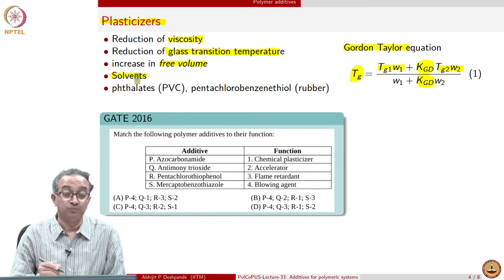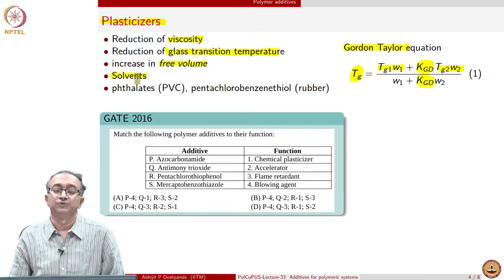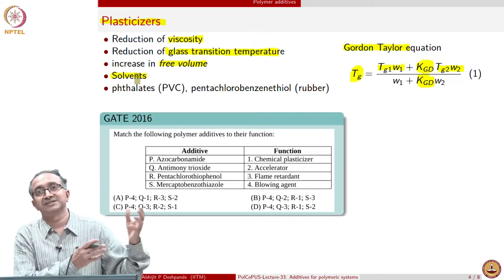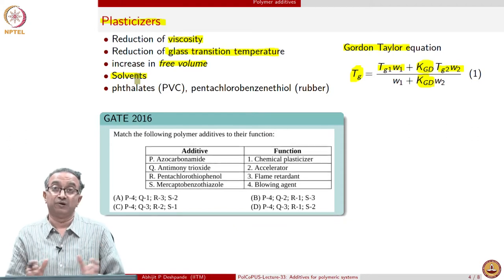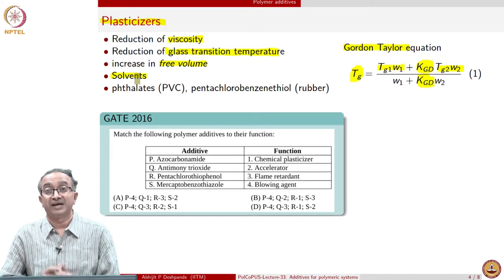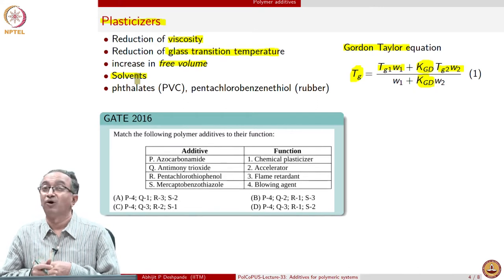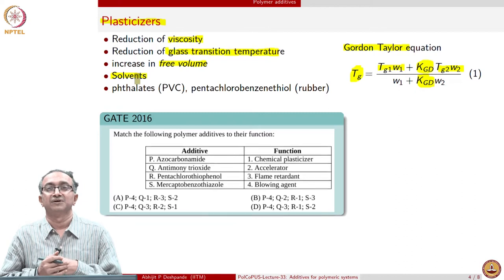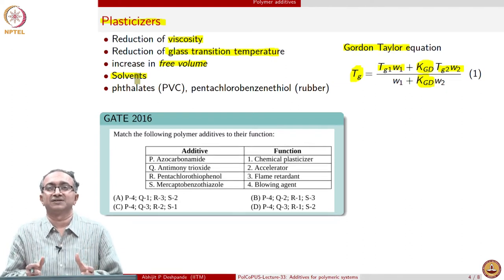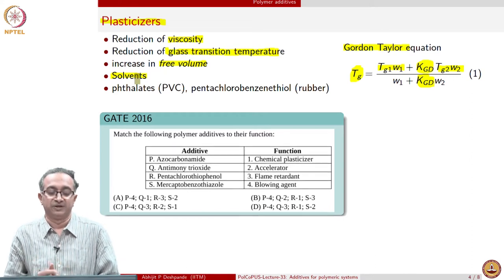Solvents and also monomers themselves can also play the role of plasticizers. Small molecules intentionally added as plasticizer, but also residual monomers and residual solvents remaining as a consequence of polymerization or earlier processing, all play a crucial role in determining final properties. As highlighted in lectures on mechanical properties, nylon — whether dry, conditioned, or with some water — has very different properties. Water interacts with macromolecular chains, or equivalently, water is a plasticizer for nylon, changing free volume and therefore changing the glass transition temperature.